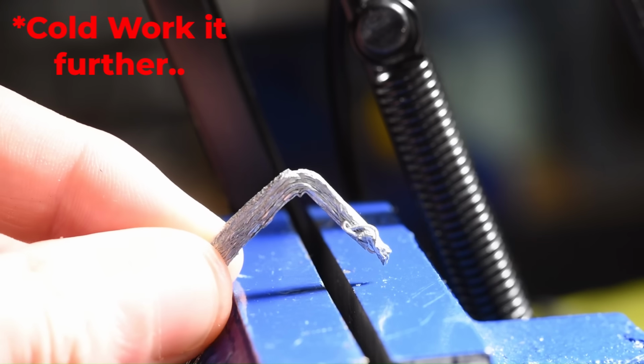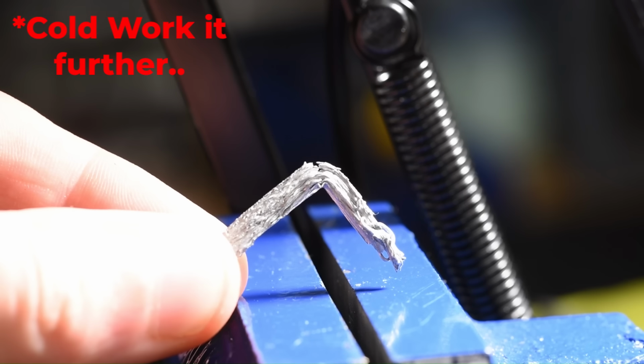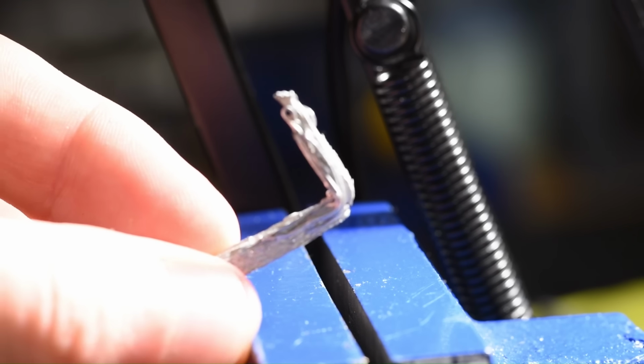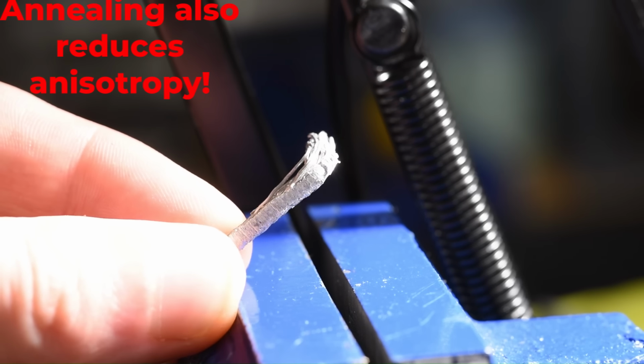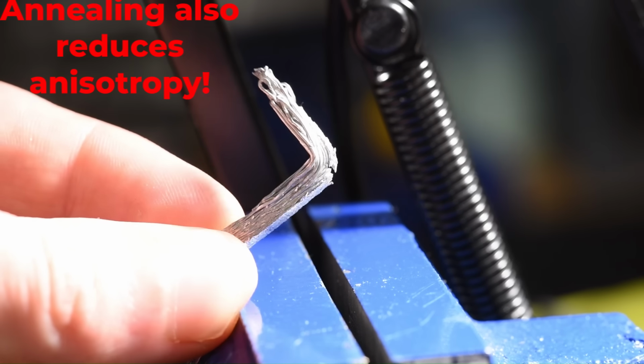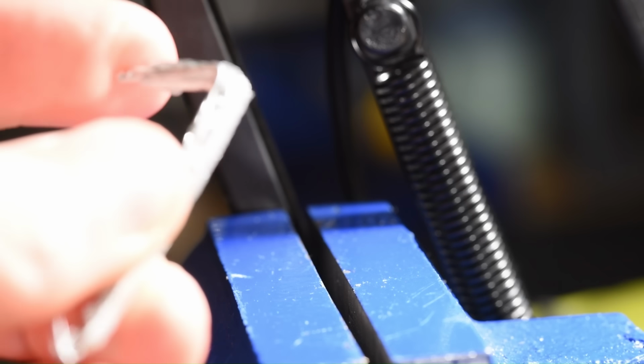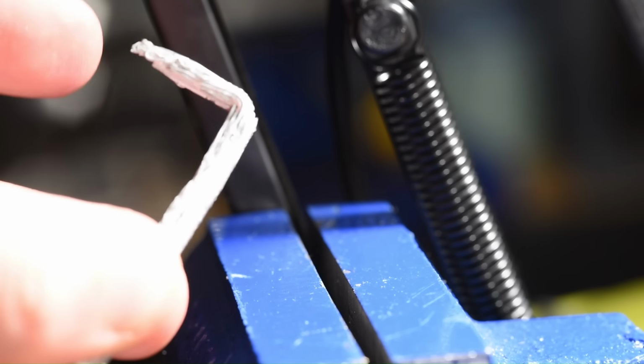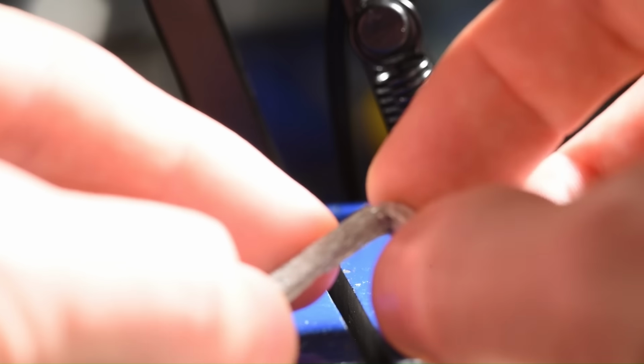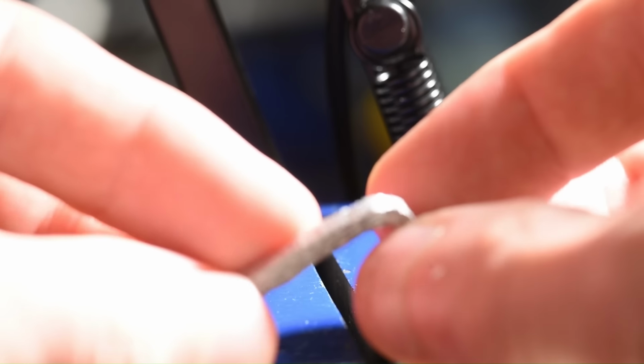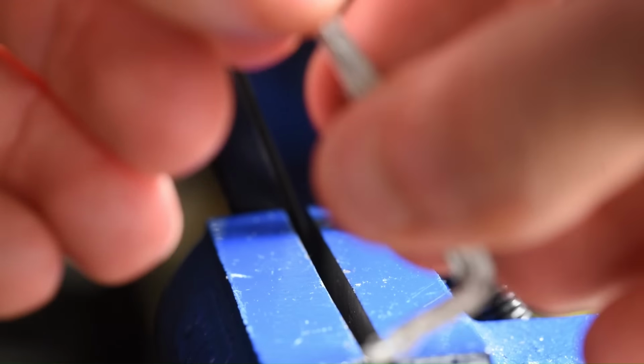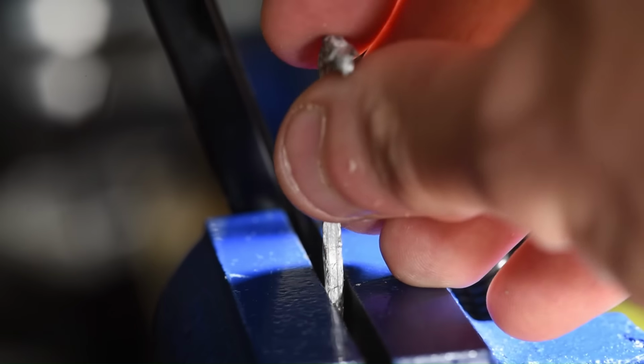It's recommended that you anneal it between working cycles to retain maximal ductility and to prevent cold cracking whenever it's folded over a sharp bend or taken around a corner or something like that. But it's good to see, and we were particularly excited by the fact that the parts, as printed, still had more than enough ductility to go through a 90-degree bend and did not fail completely in brittle fracture when bent as such, and showed no signs of delamination at the bends.